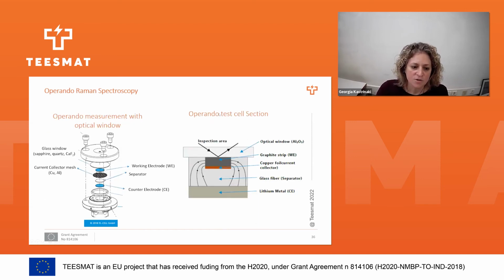Now, if we see a section of this cell here, it's quite different from the typical, for example, lithium-ion batteries that we know, because here, for a half-coin cell, we have our lithium metal on top. We have a separator, and then what the lithium sees is actually the copper foil, and on top we have our active material, which can be observed by the tool that we have on top.